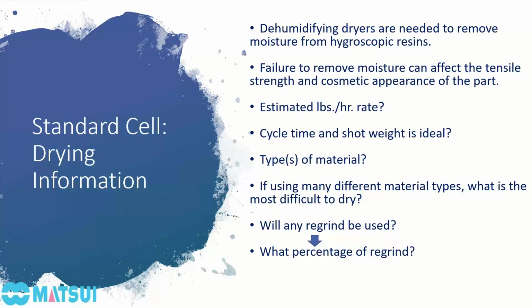So the first thing that you should determine when you're trying to decide about a dryer would be, what's your estimated pounds per hour rate? If you know what your cycle time and shot weight is, that's ideal. You will get your exact pounds per hour rate. You might be a custom molder. You're going to be running different molds. In that case, try to estimate your pounds per hour rate based on your largest mold,